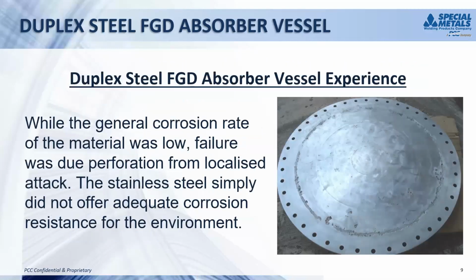This slide shows another case of crevice corrosion. In this case, this is a manhole cover, again made out of 2205 duplex steel. There was a rubber gasket used to seal the manhole cover to the manway, and you can see that ring of corrosion that exists in the center of the cover. The gasket acted like a tight crevice, and the crevice attack formed under the gasket.